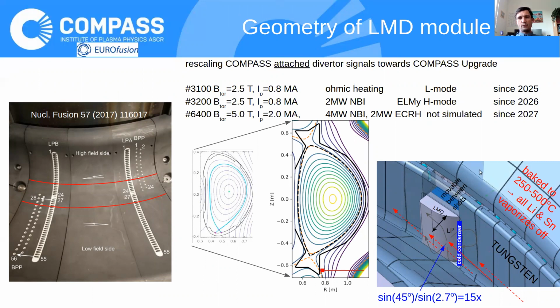Here we will introduce a liquid metal target in the beginning of 2025, hopefully into this outer divertor region, the outer strike point region of COMPASS Upgrade, and again at very high incidence angle. All the vaporized and sputtered lithium would then go to the vessel, but because the vessel will be baked to these high temperatures, it vaporizes off again, and then it will condensate somewhere on the cold condenser, which we will place somewhere in the chamber, maybe even as close as possible to the target itself, or maybe at other places. And in such a way, we will protect the main plasma from lithium and tin penetration. We hope so. It's a similar way as it's done on T11 in Russia.